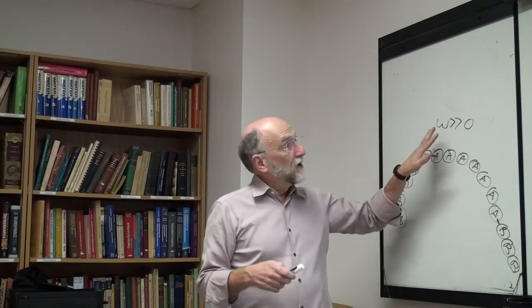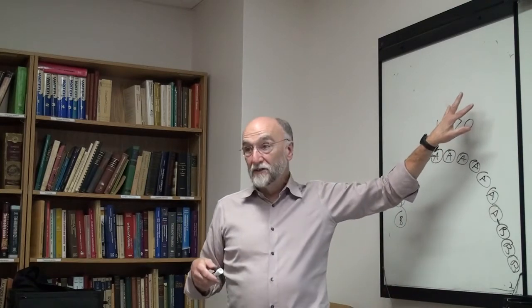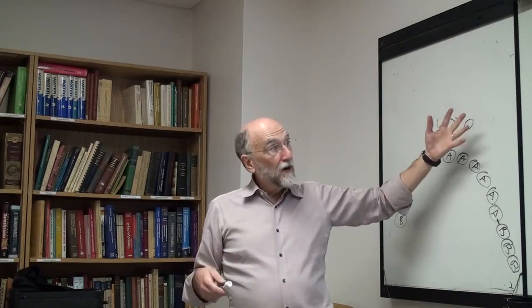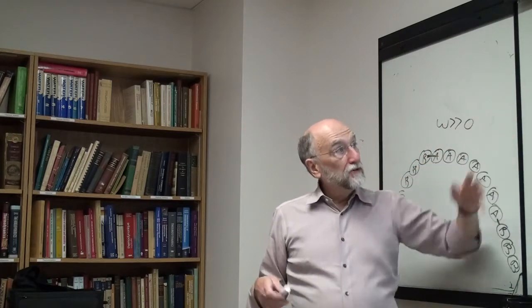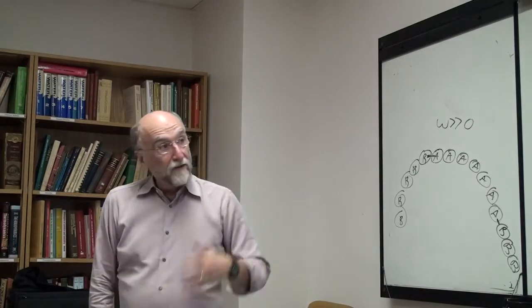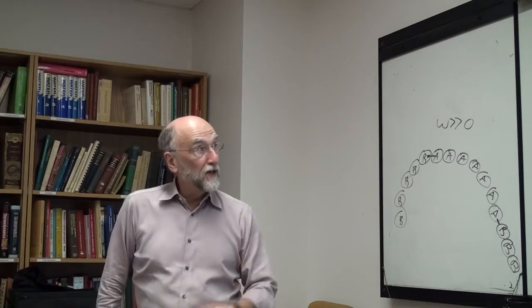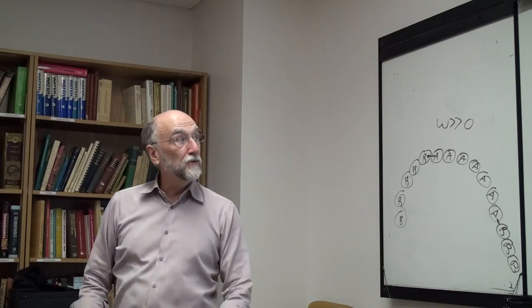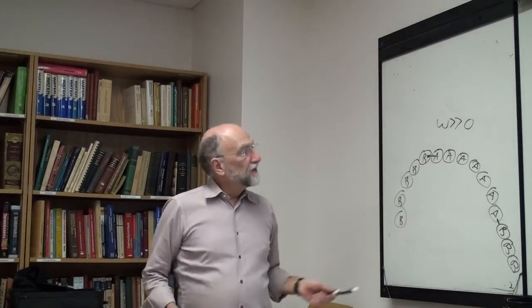So the quasi-chemical model assumes that you have only pair energies, pairs that randomly distribute themselves, and yes, you do. So it's not an artifact of the approximate equation we're using with Z greater than 2. The quasi-chemical model with Z greater than 2 in 2 and 3 dimensions does in fact give you miscibility gaps. But why is this then?